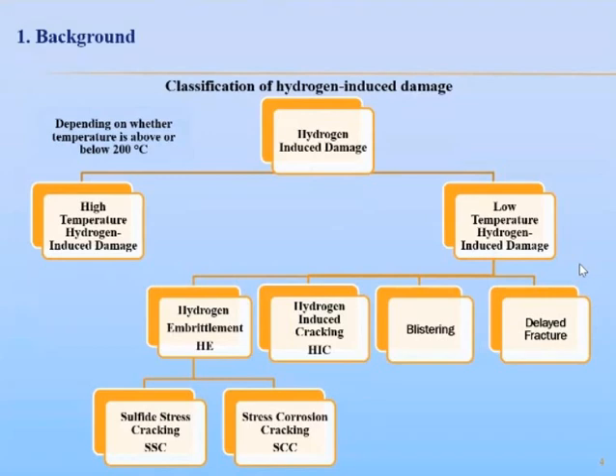Hydrogen damage is a degradation mechanism active in many industries, especially in the oil and gas and chemical industries. Here is presented a scheme with a classification of hydrogen-induced damage. Hydrogen-metal interactions can occur at high or low temperature, below 200 degrees Celsius. Therefore, hydrogen damage takes place in two different regions: elevated temperatures and temperatures at ambient and slightly above. This lecture will mainly consider low temperature hydrogen-induced damage.